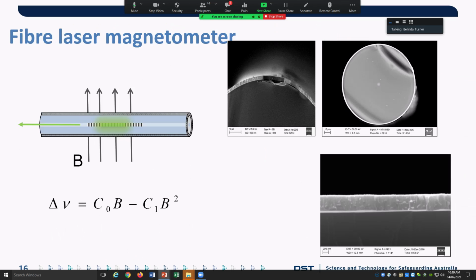So my idea was basically to take one of our fibre laser sensors, coat it with Terfenol-D or some magnetostrictive material, and in principle have a very sensitive magnetometer. Essentially you're functionalising what is the most sensitive fibre optic strain sensor as hopefully the most sensitive fibre optic magnetometer, right? So I've got some nice images - I believe this is Terfenol-D.